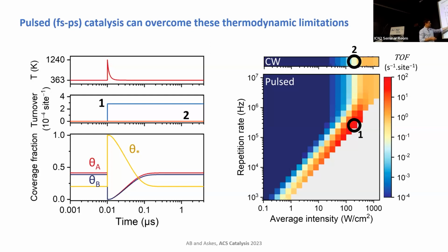If you look at the surface coverage, the catalyst is essentially almost fully coated with A and B. This is not exactly at 0.5, and there are a few empty sites because we are running this reaction at 363 K. That's not room temperature. But we have a lot of A and B on the surface, and then the pulse is coming, the catalyst is getting super hot. Everything is empty, so the fraction of empty surface sites becomes essentially 1. We empty the catalyst right away, but we have sufficient time during this heating to form a lot of product.